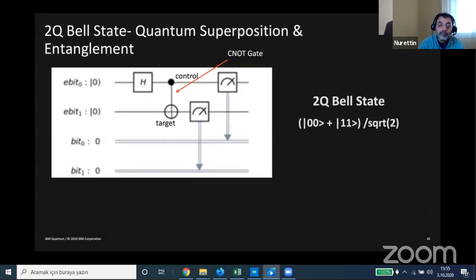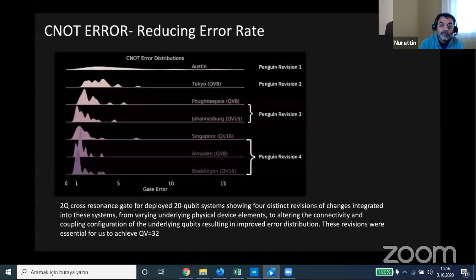However, due to errors in the CNOT gate, we don't achieve that ideal limit. And so a key feature going forward is reducing the error rates of these gates. And I forgot to mention that this H gate here does a superposition. So you do a superposition and a CNOT. So shown here is that CNOT error for different devices that we have deployed. And we have been improving this CNOT error, and we have a roadmap to improve it by roughly 2x per year. And shown here is that we can achieve errors well below 1%. As I showed in the Quantum Volume 64 paper, we were able to achieve well below that. And our roadmap prescribes that we continue to reduce this error by 2x per year.